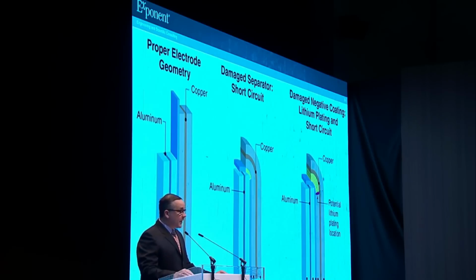Based on the available data, it's not possible to determine if one failure mode is more probable or if contributions from both failure modes might be required before the occurrence of the observed failures. However, based on our knowledge of lithium plating that is severe enough to cause cell faulting, it is more likely for this failure mode to occur later in life, after many cycles. Remember that all of these failures occurred very early in the life of the device.